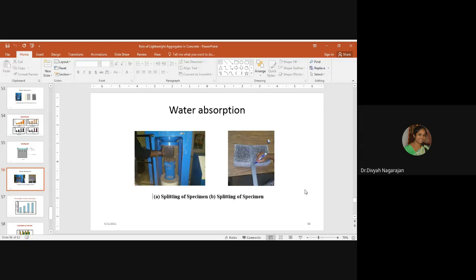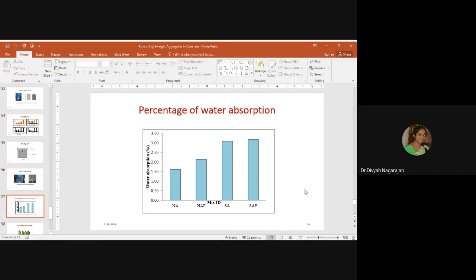Water absorption. After subjecting to 24 hours of water ponding, the specimen was split into two halves, and the water absorption plot was done. Now coming to the percentage of water absorption, on comparing the water absorption percentage of the mix subjected to ponding and sorptivity, there were no significant or large variations in the observation, because this is a long-term effect. When it is subjected to 24 hours of observation, it will directly give the water absorption, and the specimen size also plays a major role. The sorptivity and ponding tests provided almost the same water absorption percentage.